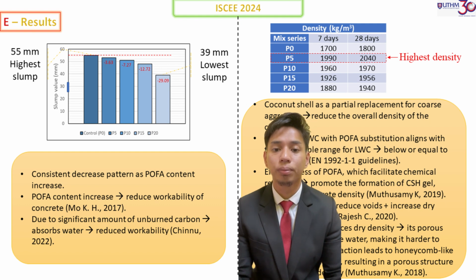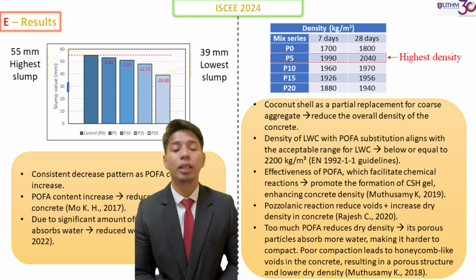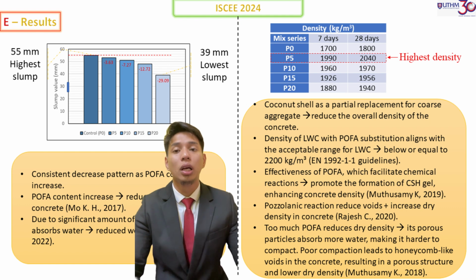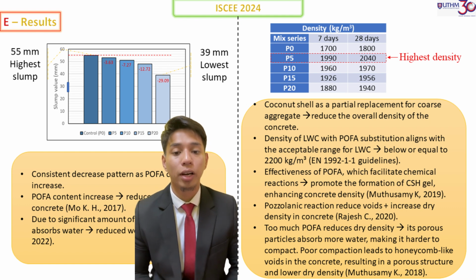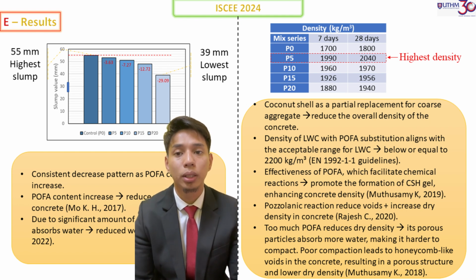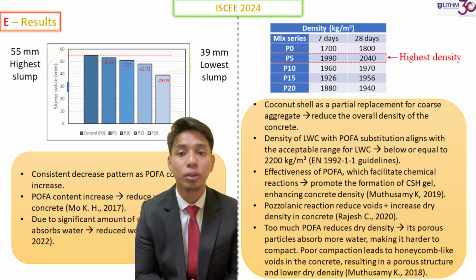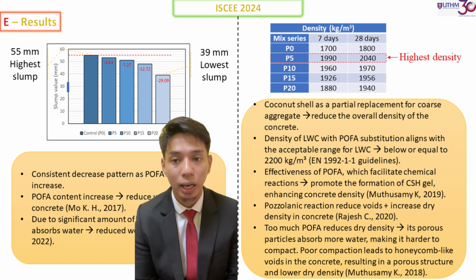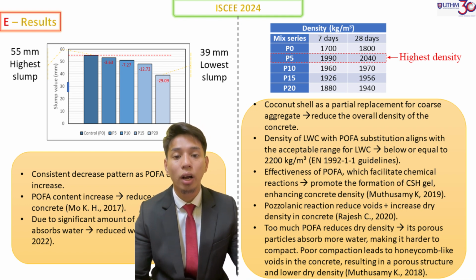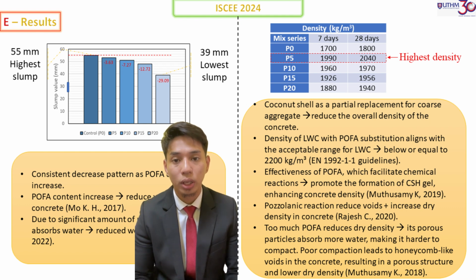So this is the result of density of concrete for each mix. The highest density belongs to the P5, which used 5% of POFA as partial cement replacement. The coconut shell as a partial replacement for coarse aggregate will reduce the overall density of the concrete. Density of LWC with POFA substitution aligns with the acceptable range for LWC, which is below or equal to 2,200 kg per meter cube.